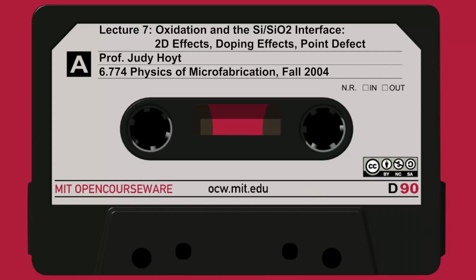So the stress effects did a reasonably good job of getting the shape right. Here at the corner it is not perfect, but it's close. The actual device shown here, the actual data seems to have a little bit more of a bird's head, so maybe the stress effects weren't perfectly modeled, but it's pretty darn close. So people spend a lot of time calibrating their stress models and their stress coefficients to try to get close to what's measured experimentally.